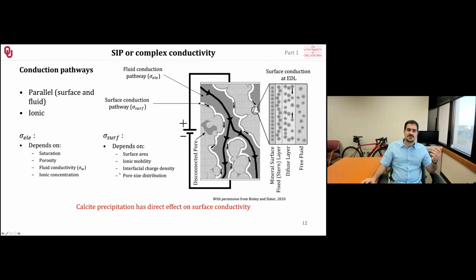There are other factors such as pore size distribution, very important. If you have a larger pore, it takes the ions longer to distribute because they need to travel a longer distance, as opposed to smaller pores, where the distance is shorter. So basically the polarization occurs in a shorter time. And the interfacial charge density, basically the amount of these positive ions that are going into the electrical double layer.